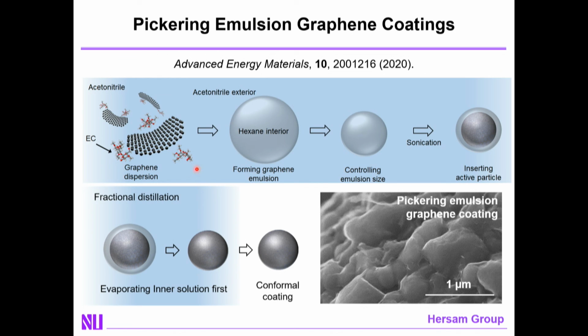This was achieved by utilizing a trick from soft matter, in particular the use of Pickering emulsions. For those of you who don't know about Pickering emulsions, how they work is you take two immiscible solvents, in this case acetonitrile and hexane. If you shake them up, you'll form an emulsion where you have small droplets of hexane in the acetonitrile. But if I just let it sit, it will eventually phase separate like oil and water. However, if I have a third party present, in this case our graphene, the graphene will be recruited to the surface of the hexane droplets. It will stabilize the interface between the two immiscible solvents, giving you a stable emulsion. So a Pickering emulsion is one where a third party, in this case graphene, stabilizes the emulsion. So what?